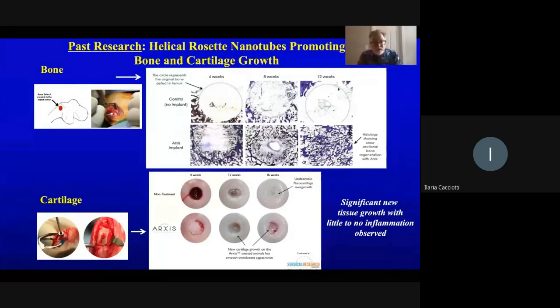They reduce inflammation, promote tissue growth. Here's a study where we injected this into a bone defect. On the top, you can see the control, no implant. After 12 weeks, bone growth did not occur. When we inject this into that same defect site, we call this material Arxis, the trade name. You can see increased bone growth. So this material is a self-assembled material, can be directly injected into bone defects and heal bone, as shown in this rabbit study that we conducted many years ago.